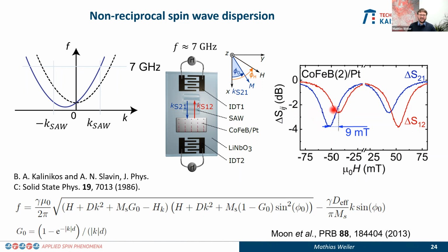So I'm not sure it will be technologically really viable in the end to get a tuning of the DMI that is sufficiently strong that you can switch on and off non-reciprocity, right? Might be very challenging to do so. It might be easier to tune it not by electric gating directly, but by using static strain again, right? By tuning the piezoelectric material that you have anyway with a DC voltage, you change the anisotropy of the material, change the anisotropy then of the magnetic material with a DC strain, and then use that to tune it. My guess would be that this could be the more viable approach than tuning the DMI directly with an electric field. But we have not done any experiments in that direction.